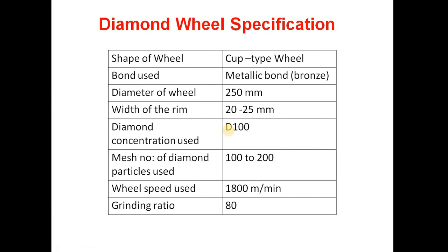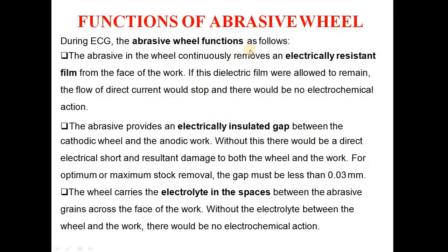So the diamond wheel has a common specification used in electrochemical grinding. It has a cup shape, metallic bronze bond, diameter of about 250 mm, and a rim width of about 20 to 25 mm. It has a diamond concentration of about D100, diamond particles of 100 to 200 micron size, wheel speed of about 1800 meters per minute, and a grinding ratio of about 80.